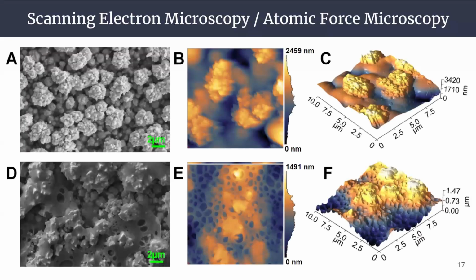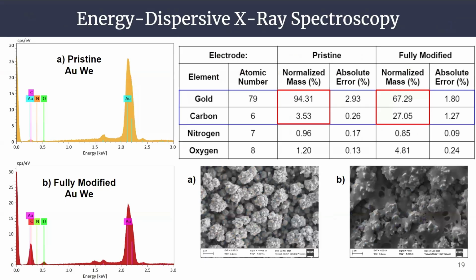Scanning electron microscopy and atomic force microscopy were used to identify the morphology of the gold particles and observe the surface modifications over the working electrode. The nature of these modifications was assessed by EDX, where an increase in the carbon mass was observed after functionalization, confirming the organic nature of the coating.